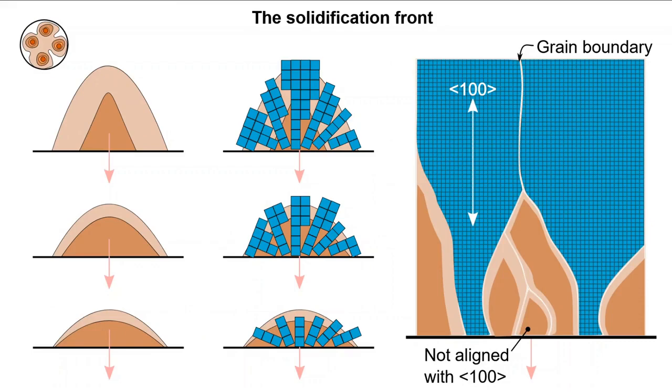What I've described here is directional solidification with the combined effects of segregation on top of crystal growth. These are not mutually exclusive, as both would occur even in pure metals. If there was no appreciable directionality with respect to heat transfer, then this type of solidification front would still occur, albeit in a random orientation to generate the equiaxed grains described in Part 1. Directional solidification generates columnar grains, as depicted here. Directional solidification, along with segregation, gives rise to further development of texture and resulting anisotropy.